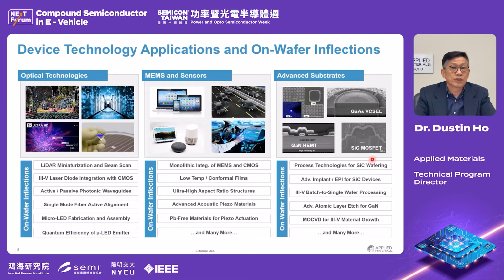This also brings out a new substrate, from silicon to compound semiconductors such as gallium arsenide, silicon carbide, and gallium nitride. So the process technology for silicon carbide wafering is very important, in the high temperature implanter and epi for silicon carbide devices, and the transition to 6-inch and 8-inch, just like silicon 30 years ago was the transition from batch to single wafer processing. Then also ALD and ALE for the GaN will be very important, and MOCVD for the III-V material growth, so it can reduce the cost for the epitaxy and more.